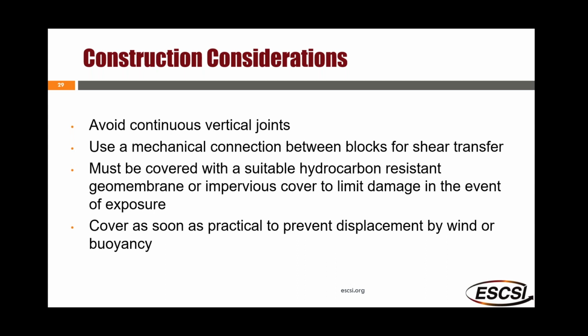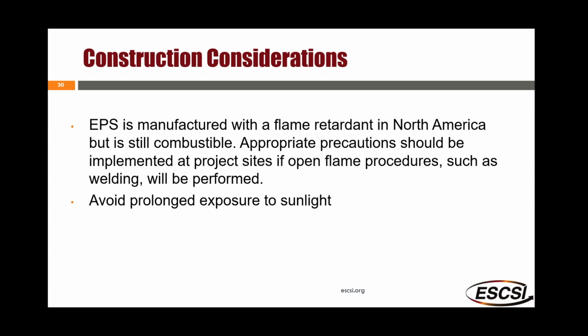And you should cover the EPS with a suitable hydrocarbon resistant membrane or some sort of impervious cover to limit damage in the event of a hydrocarbon exposure. And you should cover it as soon as practical to prevent displacement by wind or water. Another thing to consider is EPS is manufactured in North America with a flame retardant, but it's still somewhat combustible. So open flame procedures such as welding should be carefully monitored in and around an EPS embankment.